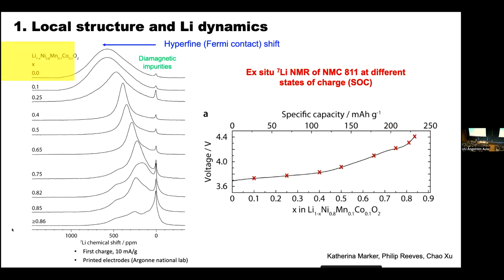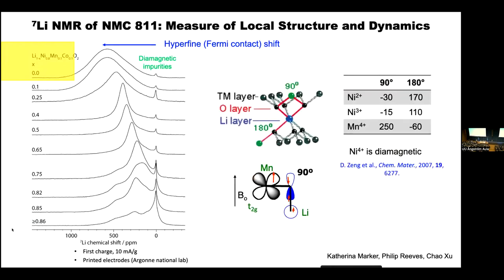So this is rather old work done by my former postdoc, Katharina Märker, who looked at NMC in an ex situ mode by NMR spectroscopy. What we do is make lots of little batteries, take them apart, and then run NMR spectroscopy on them, all the way from the fully lithiated material to the almost completely delithiated material. Over the years, we've developed a whole language to understand the NMR spectra, where we can interpret the peak positions in terms of what's known as a hyperfine shift, which is a measure of how much unpaired spin density starts off at the paramagnetic ions, goes through the bonds, and goes to the lithiums, which are our probe nuclei, but also where the action is.